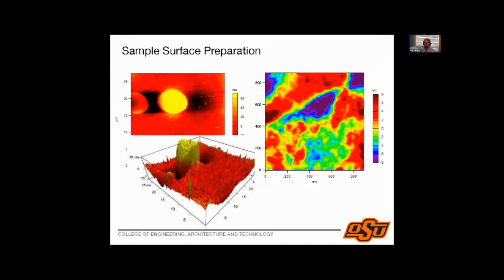So you want the height of the region that you're looking at to be much smaller than the depth of indentation. So if we look at, this is a carbon fiber, for example, and we are looking at a 3D mapping over here. This is the carbon fiber. This is the epoxy matrix. If we pick this tiny area in here, we look at this image to the right, then I see a region of a micron by micron, approximately. The maximum height variation I have is from -8 to 8 nanometers. So this is relatively flat. That means I can carry out my measurements with indentation over here.